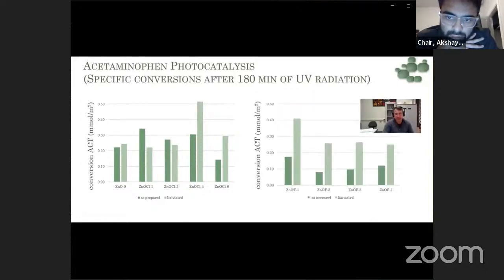And for fluorides, the effect is very, very important. You can see here powders with a very low concentration of fluoride. We have a very important increase in the photocatalytic activity after lixiviation. And then the fluoride and chloride on the surface is not so good, but is necessary in grain boundaries.